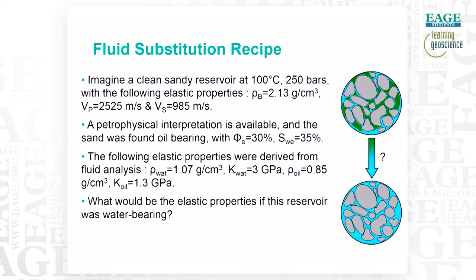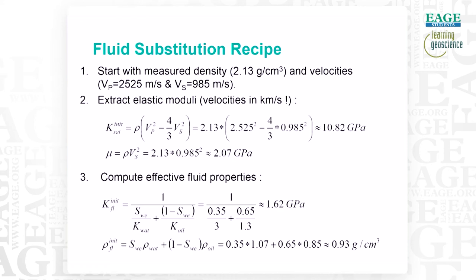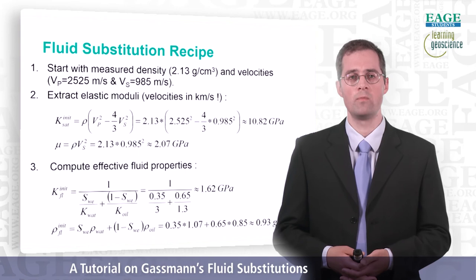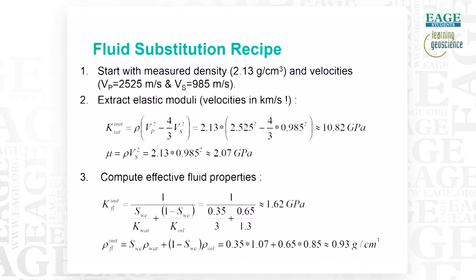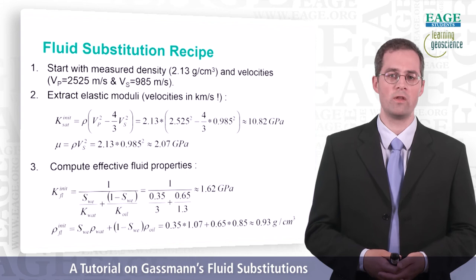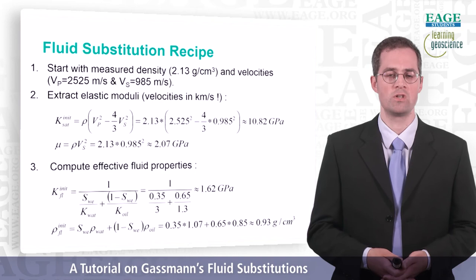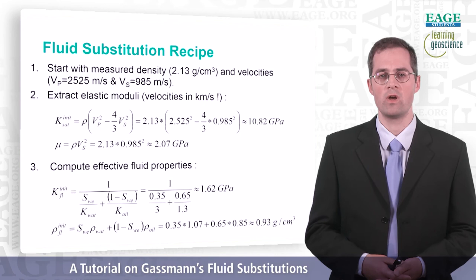So the question we have is, what would be the elastic properties of this reservoir if it was water-bearing? So let's start with the measured density and P and S wave velocities. First of all, we must extract the elastic moduli from these velocities and density. Remember that your velocities should be in kilometer per second if you want the bulk and shear moduli to be in gigapascal. So it's quite easy to compute the bulk modulus. It's just the product of density multiplied by square the P wave velocity minus 4/3 of square the S wave velocity, which in the end gives us an initial saturated bulk modulus of around 11 gigapascal. The shear modulus is even easier to compute.